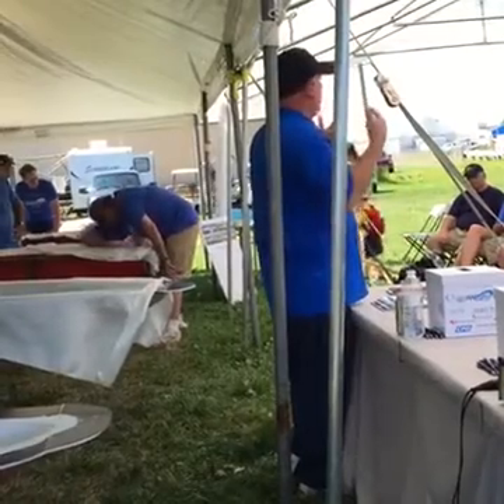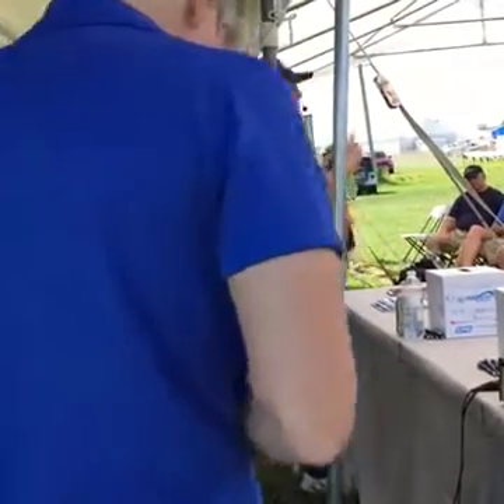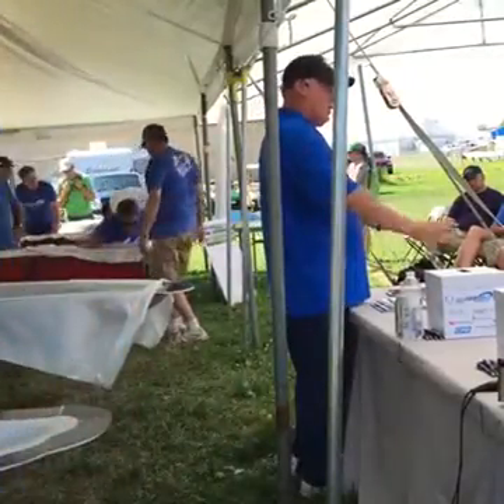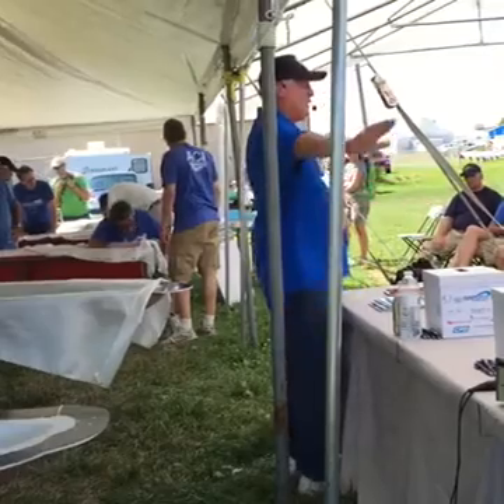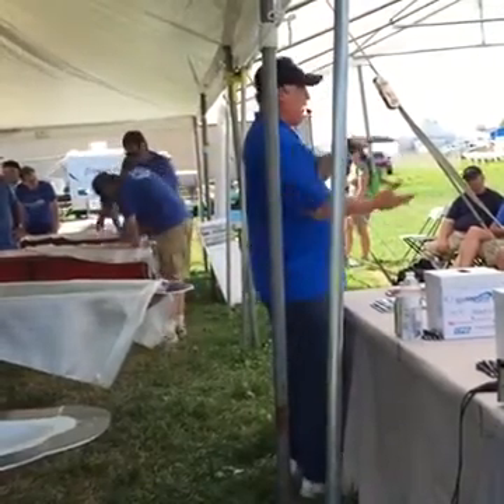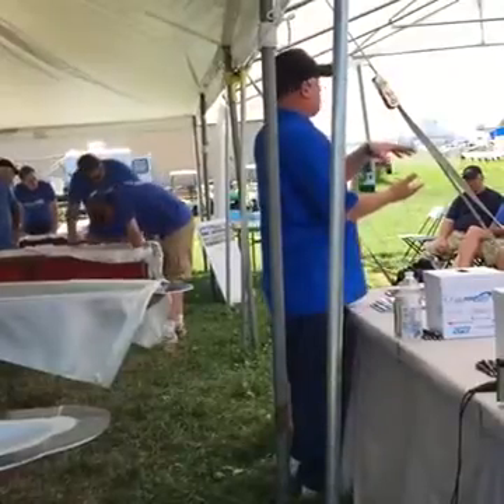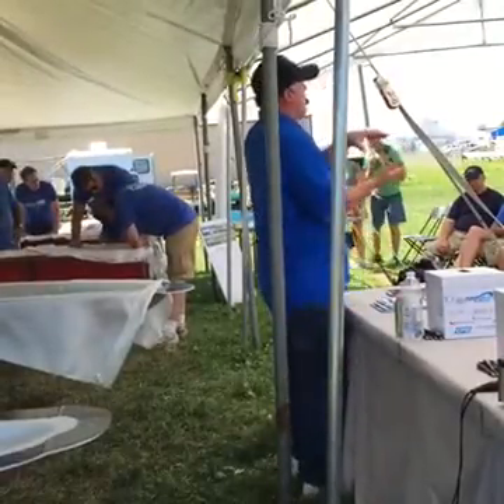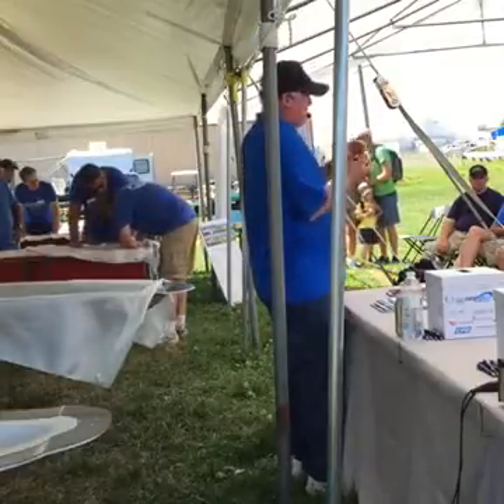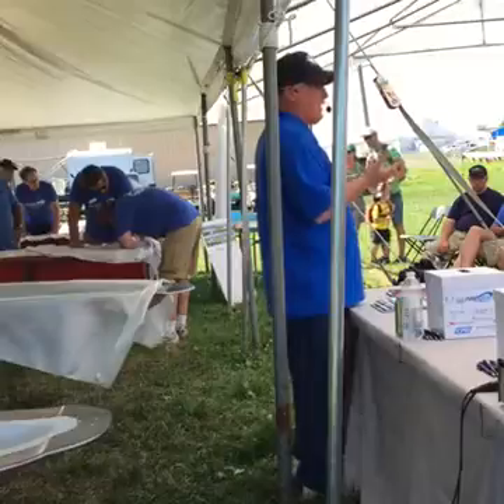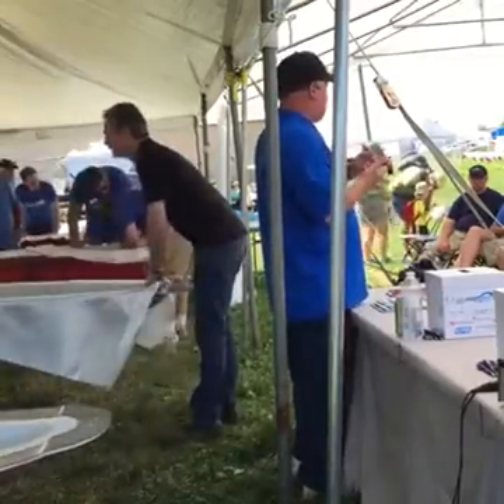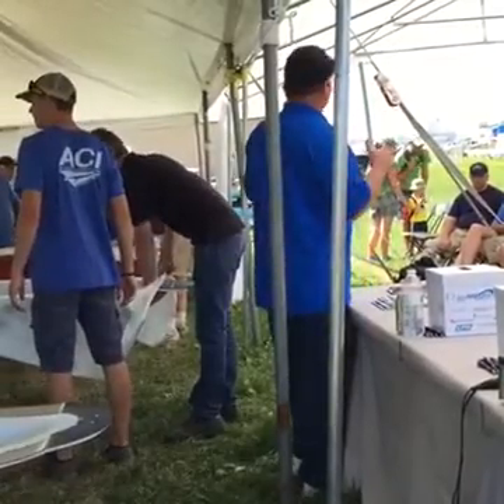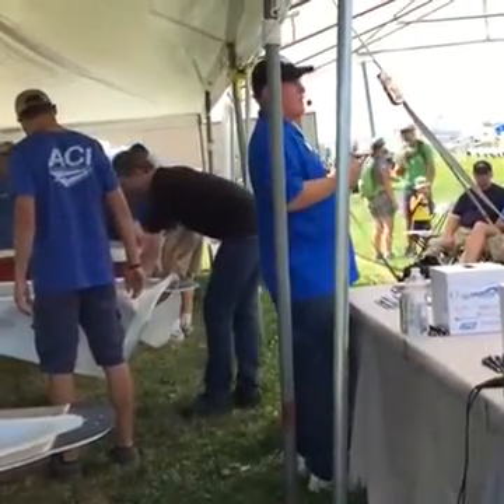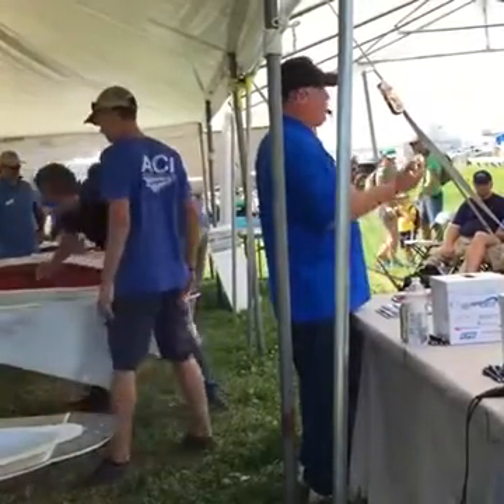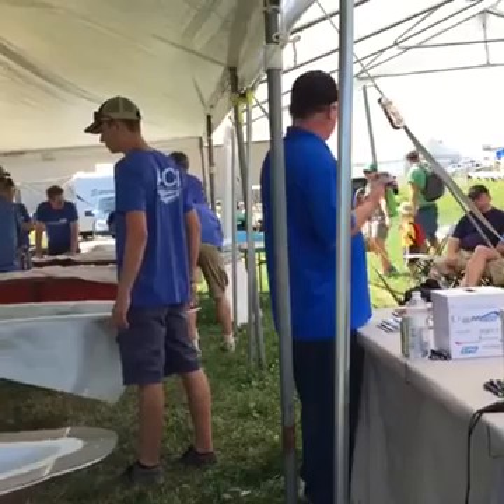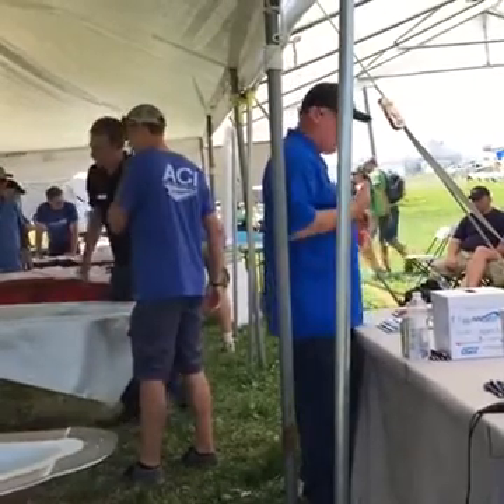Well, then it dawned on me, I've got to vent the 2 bags. So I would build the first bag, and then I would put a breather on top of the first bag, and then build the second bag to the outside perimeter of the first bag. Now I can apply pressure to the first bag as though it's part of the laminate stack. Now, a lot of you probably haven't seen this, but some vinyl esters, polyesters, acrylate esters, all resin systems, some of them are highly susceptible to moisture. So if you don't have a super dry environment, you can create a lot of problems with your resin system, and they can outgas and they can oil under certain vacuum levels.